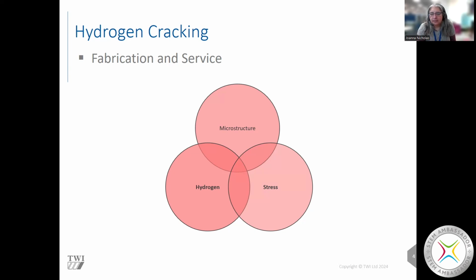So avoiding the stress, well, we're going to want to apply stresses. So we're going to want to apply loads to the component during service. So that's not really something we can do much about. The hydrogen, well, we can modify it a bit, but it's generally there. The thing that we can really do, particularly in welding, is modify the microstructure. If we modify the microstructure, then we can usually make it small enough so that it doesn't interact with the hydrogen or stress anymore, and the risk of cracking is gone. So by modifying the microstructure, that modifies the hardness, and that results in a better outcome.